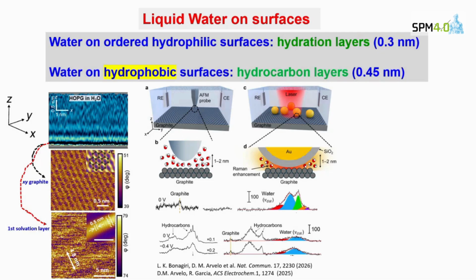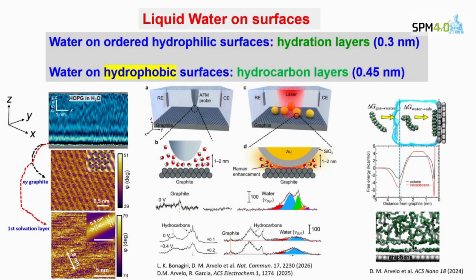Every 10 billion, you count 1 hydrocarbon. So that's nothing. However, thermodynamically, even though the amount of these hydrocarbons in the water or in the environment is really negligible, trace amounts, these hydrocarbons love to sit near a hydrophobic surface. So when they are in the water, they diffuse. Eventually, they reach the hydrophobic surface and they stick to it because the free energy is favorable.